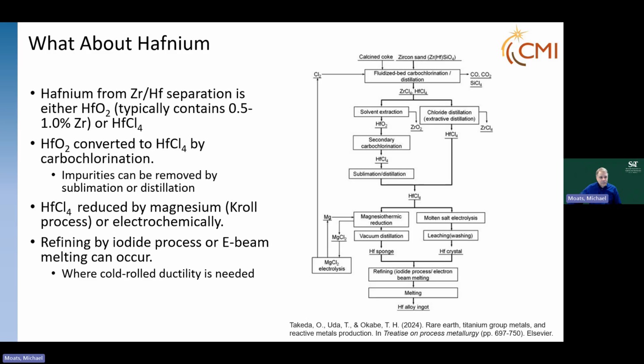electrolysis. If this purity, this 0.5 to 1% zirconium, is not good enough purity for what you're trying, you can refine it. There's an older process called the iodide process, or you can do what's called e-beam melting, and that's needed when you need a good cold roll ductility for the hafnium.